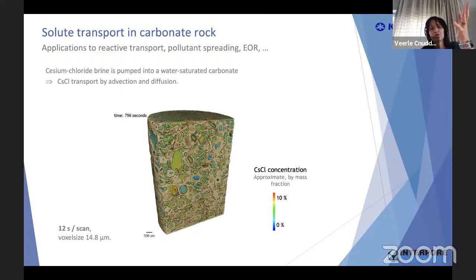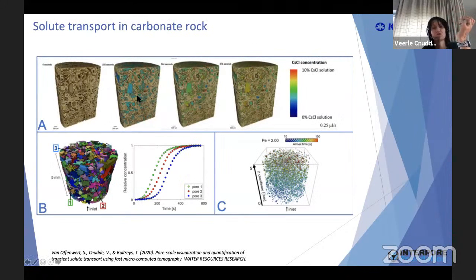You don't only look at the images to see what's happening, you can quantify a lot. You can quantify the concentration of salt inside each pore, and how the relative concentration changes over time. You can say, okay, I want to monitor this virtual pore. Of course, this is an open pore network where all pores are interconnected, but if you virtually classify them based on pore throats and pore bodies, you can distinguish them, and determine, for instance, the arrival time of the salt in each pore and visualize this.